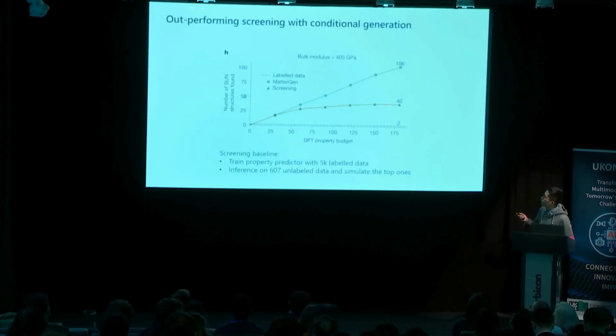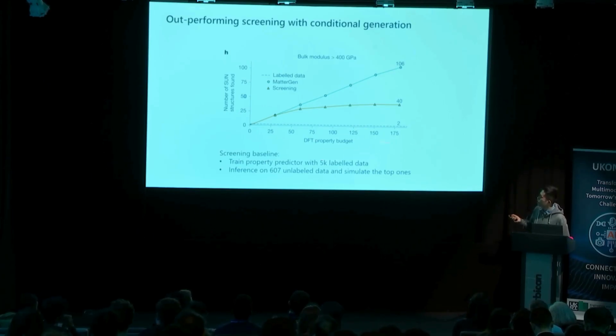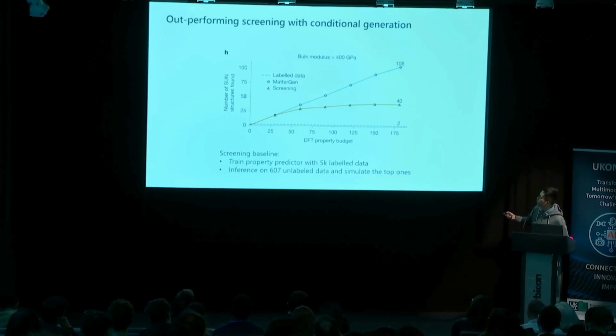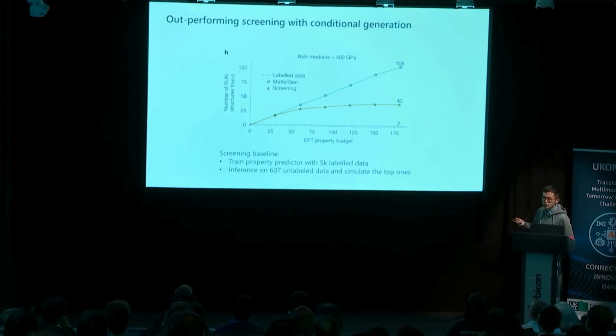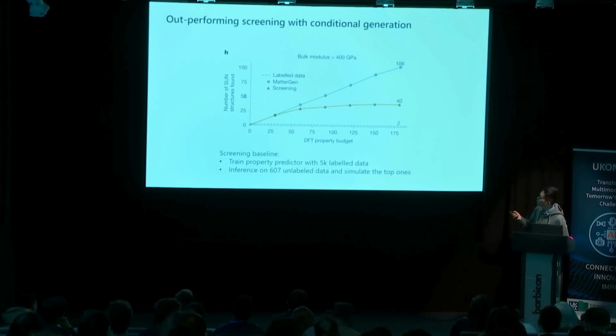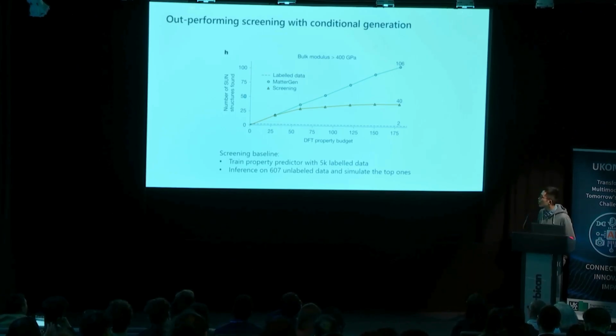So this is another example where this really shows the advantage of these generative models. Here the x-axis is the number of DFT calculations, how many times you calculate. The y-axis is the number of materials you find. You will see that with the generative model, as you keep increasing your budget, you're finding more and more materials that are super hard, which is above bulk modulus of 400 gigapascal. But with traditional screening-based methods, you saturate. So this is why your generative model can explore a much bigger regime, finding a lot more of these novel materials compared with what people have traditionally been doing with screening-based approaches.